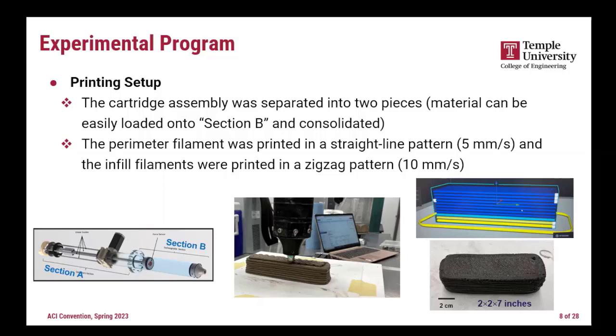So here you see the example of the printing. As I said, 2 by 2 by 7 inch. So we can cure them, we can cut them for compression or flexural experiments. Regarding the pattern of printing, we use this: basically the outer or perimeter layers are more straight lines. The infill is more zigzag. And the main reason for this is that we got better dimensional stability from this pattern.